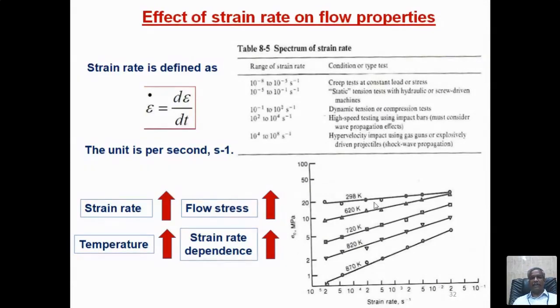People used to test for 10,000 hours. You call it how many days it is. So you have to test for 1 year, and it's a very, very small strain you will apply. In the static tension test, you see 10 power minus 5 to 10 power minus 1. Normally for a screw-driven machine or hydraulic machine, this condition will be applied, the strain rate